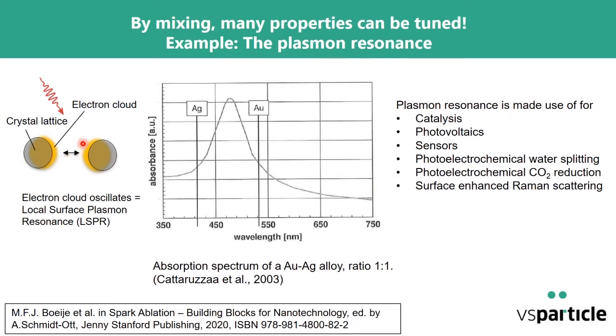And if the resonance frequency that they have corresponds to the frequency of the incoming radiation, then you get resonance. And if you measure the absorption spectrum as a function of the wavelength, then you see that for a specific wavelength, the absorption is highest, and that is where this resonance occurs. That's also the phenomenon that gives a metal its color. This is here for a mixture of silver and gold mixed in a 1-to-1 ratio. And you see that the plasmon frequency for that mixture is just between the cases for pure silver and pure gold. For pure silver, the resonance would be here, and for pure gold, it would be here. And so by adjusting this ratio, of course, what you can do is tune the plasmon resonance.